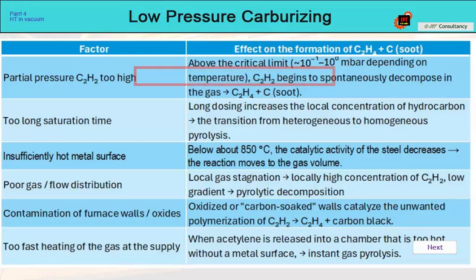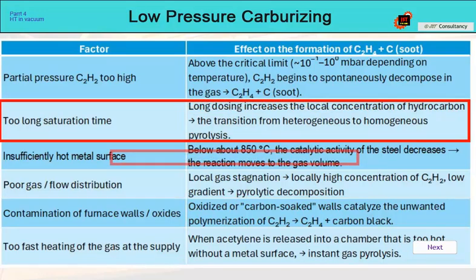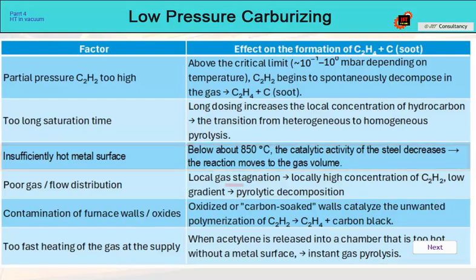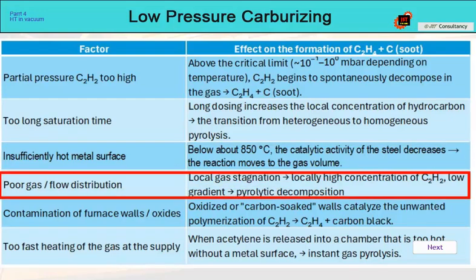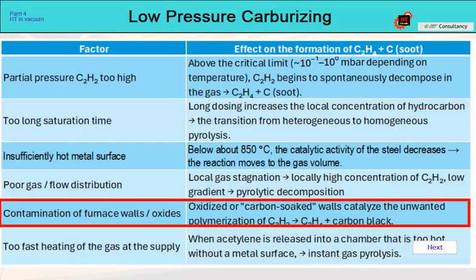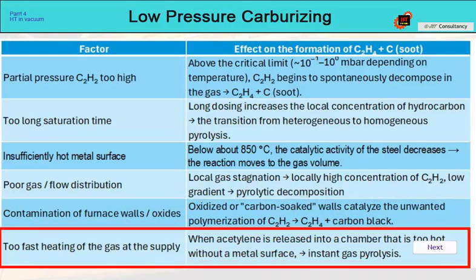Signs of inappropriate process settings are listed in the table: too high partial pressure of acetylene, too long a saturation period, insufficiently heated surface of the batch and furnace, low gas flow or its distribution in the furnace, contamination of the furnace walls with carbon, or too fast heating of the gas at the supply. In optimal carburizing, the acetylene content drops sharply after injection into the furnace. The amount of ethylene is close to zero, and at the same time the hydrogen content increases slightly. In risky carburizing, the accompanying phenomena are a high acetylene content, a sharp increase in ethylene, and hydrogen may also increase sharply at the same time.